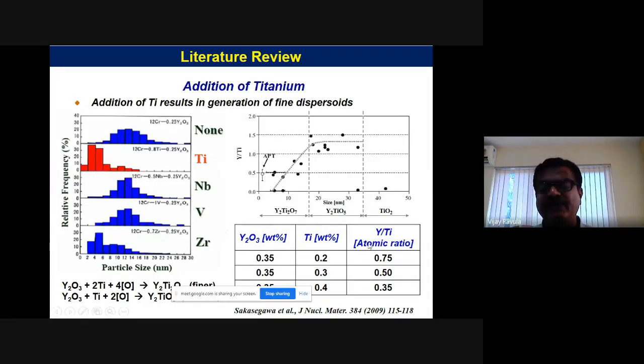And then when you're looking at it, it is different. When you're coming to the lower, this is the particle size and the Y to Ti ratio. If you maintain it around 0.5 to 1, then the final size will be finer and finer. And when we are looking at this concentration, 0.35 and 0.2%, it comes to around 0.75. So that's why you can get very fine particles.